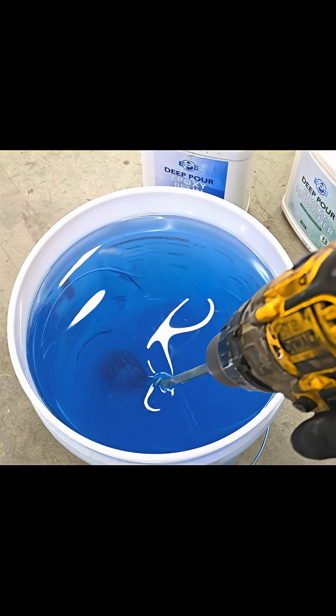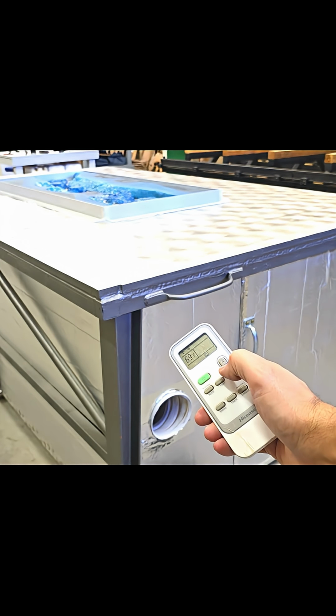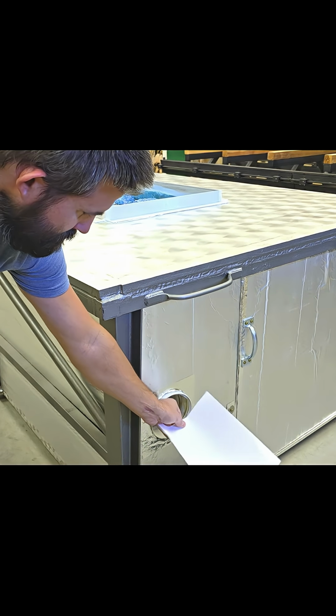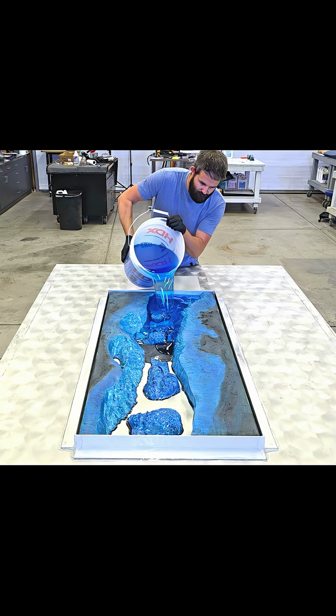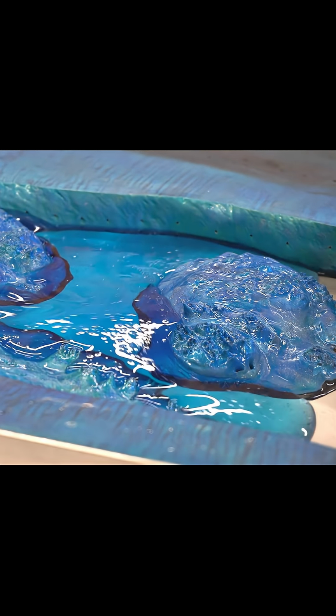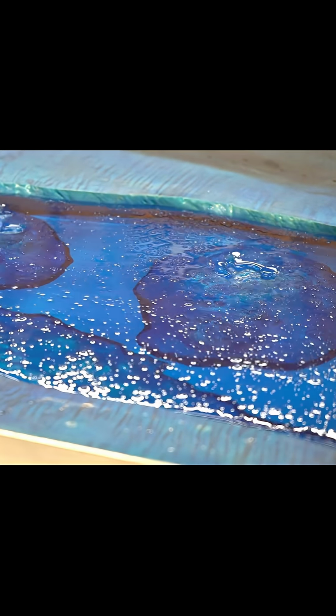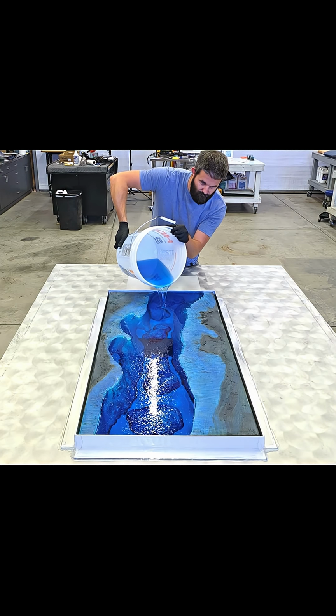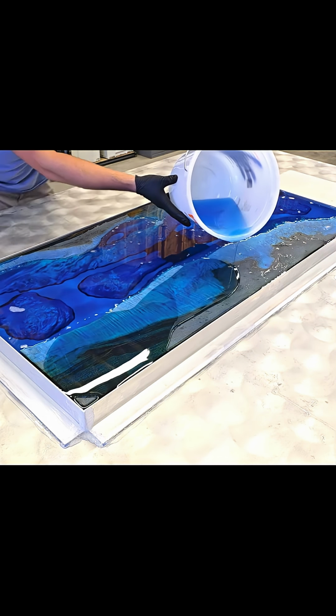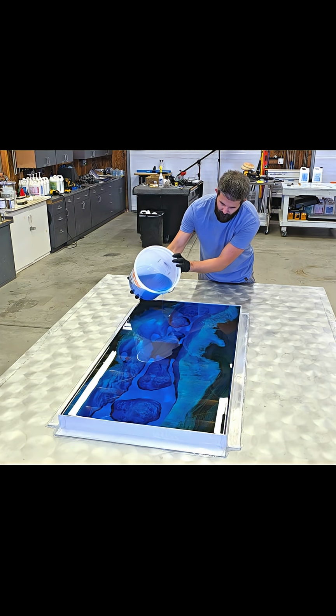I mixed up 5 gallons of deep pour resin from Easy Pour Epoxy and then turned on the AC unit to get ready for the pour. The temperature of the resin when I poured it was 95 degrees Fahrenheit. It was already starting to heat up in the mixing bucket due to how deep it was. As soon as I poured it into the table, the temperature dropped down to 70 degrees.